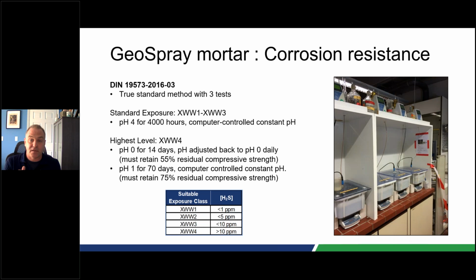And that certification for levels 1 through 3, so it's listed here as XWW1 and XWW3. Those are abbreviations for some long German words that I'm not going to try to pronounce. But the pH, they do a pH of 4,000 hour soak where the material is constantly controlled to a pH of 4. And in that case, they measure the level of corrosion and they rate it in one of those 3 categories based on the loss of material, and they kind of rate it for a given value of 1, 5, or less than 10 ppm, which is shown in the chart.